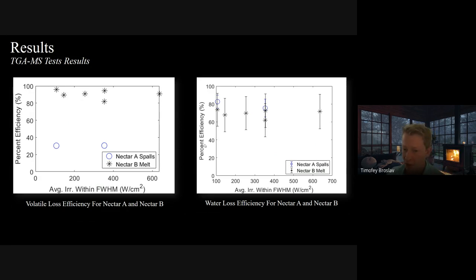However, compared to the water loss efficiency, so did it lose all the water that it can? It was basically on par with Nectar B, which got to a much hotter surface temperature than Nectar A. Once again, though they had the same water loss efficiency, Nectar A did produce more water. This is tied to the fact that its surface was constantly being refreshed.